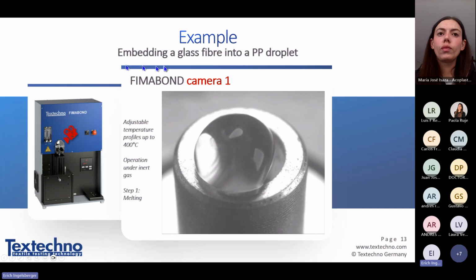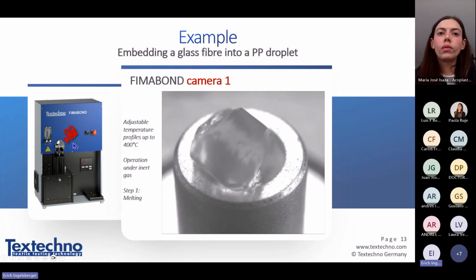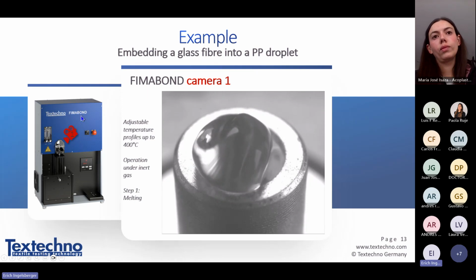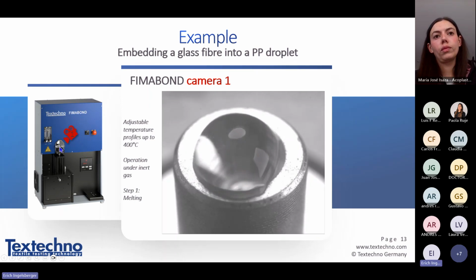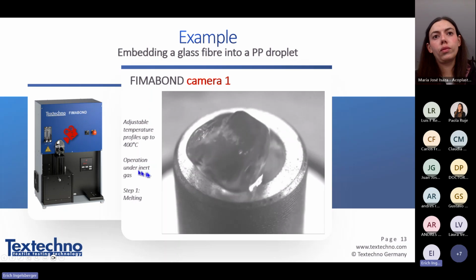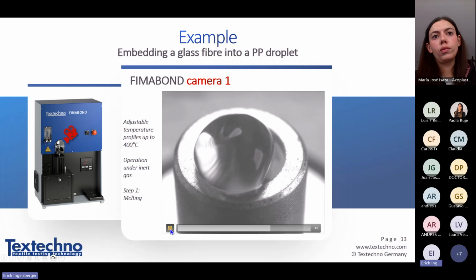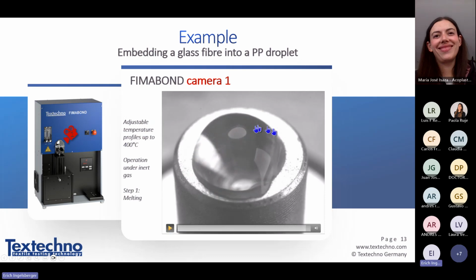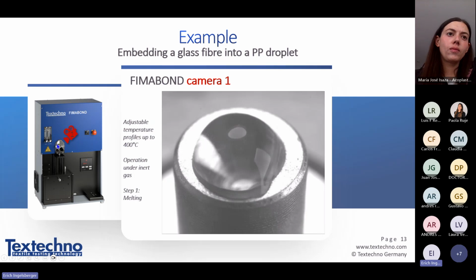This image is taken by a camera which is inside the Fimabond, looking at the test specimen. I would like to mention, at the top you can see these elliptical light reflections. This is coming from a lamp on the other side. By clever placement of the illumination and camera system, we reach that the center of this elliptical light reflection is precisely on top of the matrix drop of the sphere.